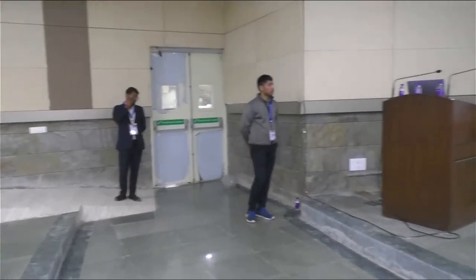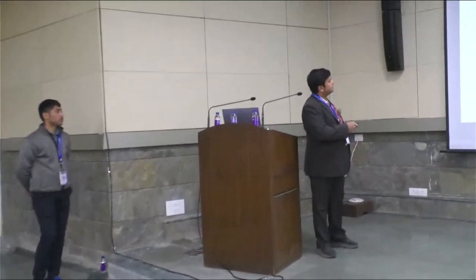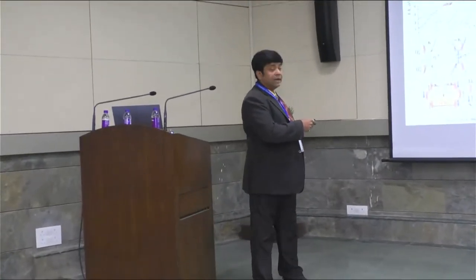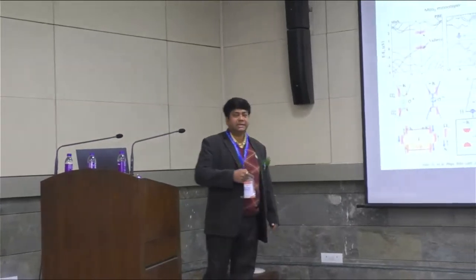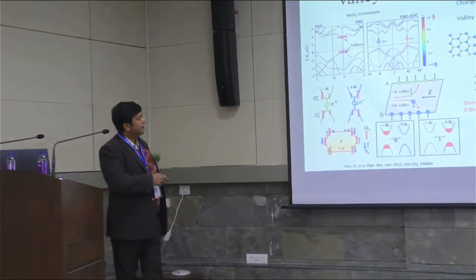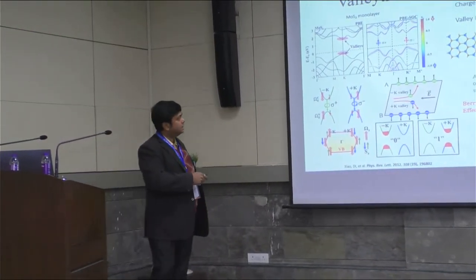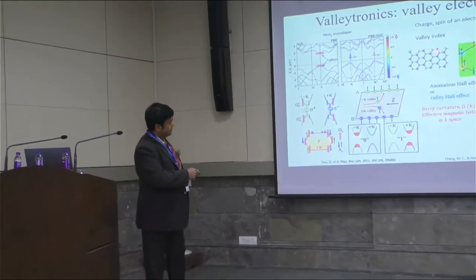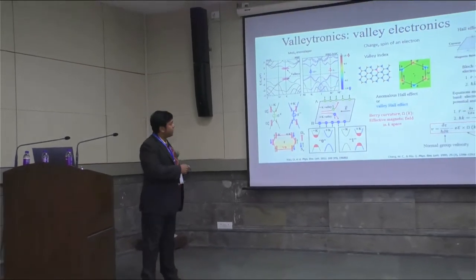Likewise, the single layer MoS2 shows valleytronic properties, the Valley Hall effect. I'll be talking about that in the next few slides. The bilayer doesn't show it. As you can see here, for the bilayer, the curve is flat, the Valley Hall voltage doesn't vary with the voltage. Now, apart from the charge and the spin degrees of freedom of an electron, another degree of freedom arises in a single layer MoS2. As you can see, the inversion symmetry is broken here. This is the top view of MoS2. The two atoms are different here.